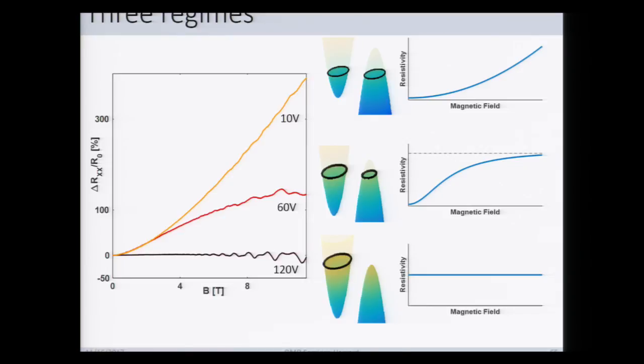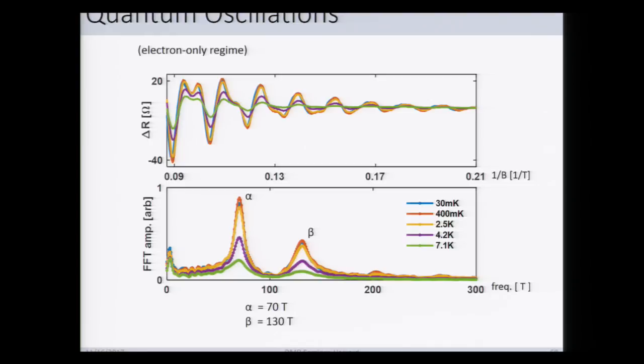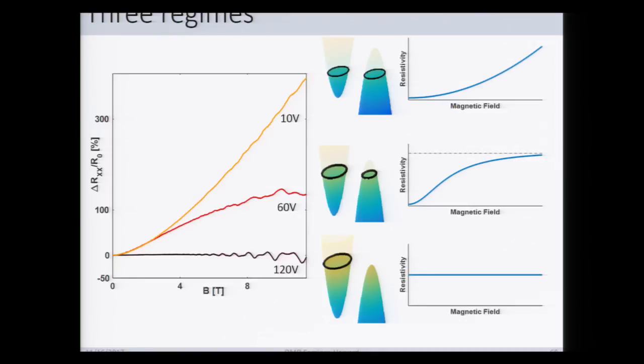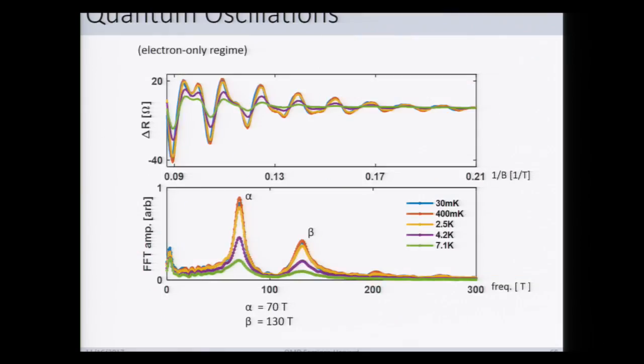So we also have a Hall bar geometry, so we can measure the Hall effect and compare, and we see indeed that at these large gate voltages, the holes are completely depleted out of the system, and we have an electron-only device. You may also notice that we have these nice little wiggles here. These are actually quantum oscillations that are indicative of high mobility in our samples due to Landau quantization. So this is the change in resistance as a function of inverse magnetic field for this electron-only regime at high gate voltage. And we see, if you're used to looking at these things, you can tell that there's two frequencies here. By taking the Fourier transform, we can see that quite explicitly.